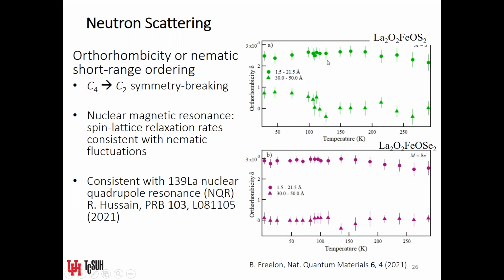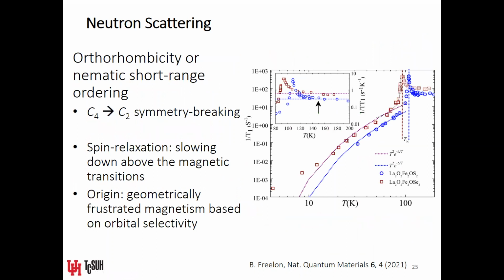All right. I'm almost finished. Let me just make a couple of comments. The actual onset of the nematic fluctuations in this material occurs over a fairly broad temperature scale. We actually see nematic fluctuations above the Néel temperature, in the high temperature or disordered regime. And it turns out that people have observed nematic fluctuations also at high temperatures above the structural phase transition temperature, as well as below.